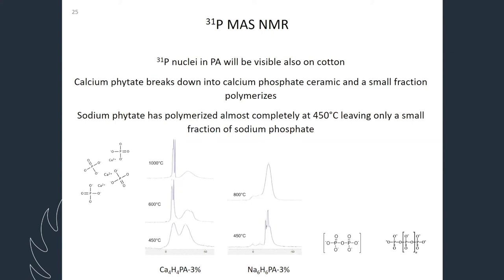So here we can see we have treated cotton with calcium and sodium phytates. So at 450 degrees, it has started to polymerize in both cases. And the sodium version is almost completely polymerized at 800. But the calcium has formed the calcium phosphate, mostly those sharp narrow peaks around zero, and then the broader peak around minus 25, that's the polyphosphate. So it's a mixture of calcium phosphate and polyphosphates that has formed.